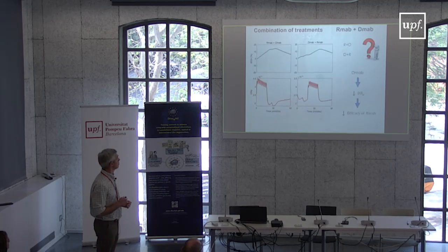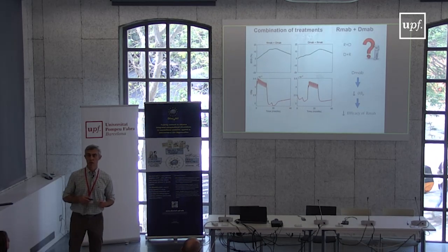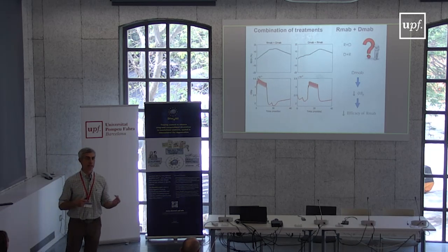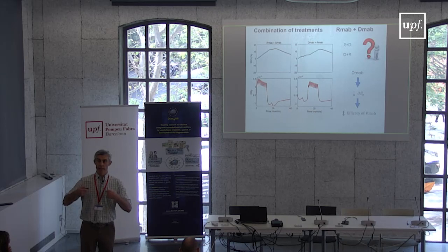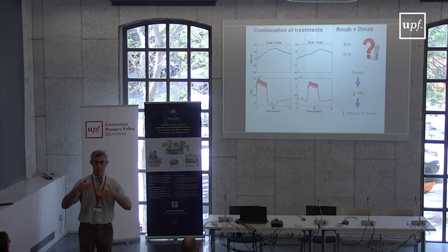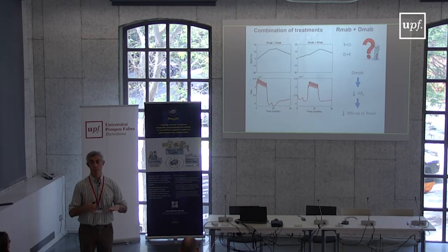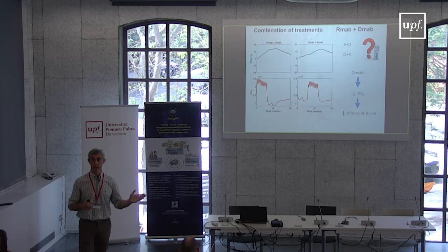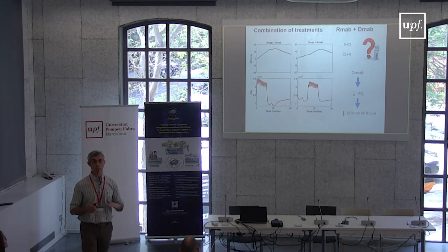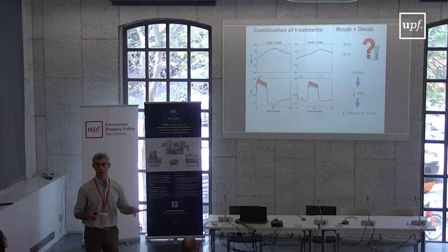Why? Well, think of what the anabolic and anticatabolic treatments do. Anabolic enhance bone formation, and anticatabolic just freeze bone turnover. So what you have here is what you will get. You can mineralize your old bone, and that's why you gain bone. You gain bone mass, because you're mineralizing your existing bone. But you're not gaining bone volume. You're just mineralizing what you have. And that's not a very good option.